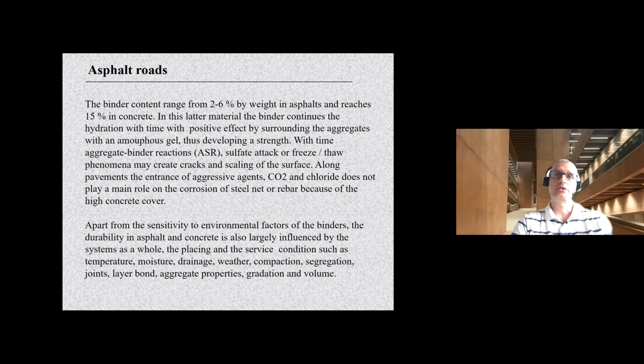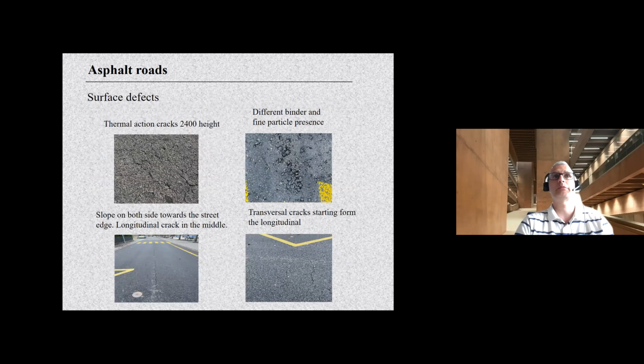It's also important to notice that both concrete and asphalt need to be considered as systems, with the different pavement layers on the asphalt and with the concrete material or slab and the foundation, so that some of the working issues such as placing or the service condition, temperature, weather, compaction, segregation, type of joints, aggregate and gradation and volume all play, or may play, a significant role in the durability of this type of pavement.